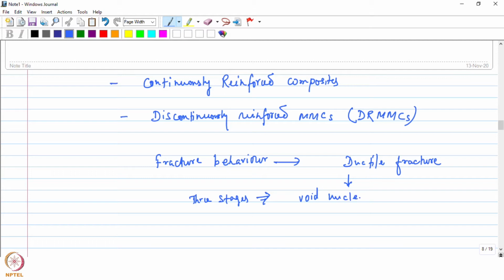Void nucleation, growth, and coalescence. Right, so this is the main mechanism of failure in ductile metals. First, as you load it, voids will nucleate and then these voids will grow, and ultimately when the voids coincide, they will coalesce into bigger voids, and that would ultimately lead to the fracture of the material. Okay. So when you have these particles dispersed in the matrix, we need to see how this nucleation and growth behavior will change.